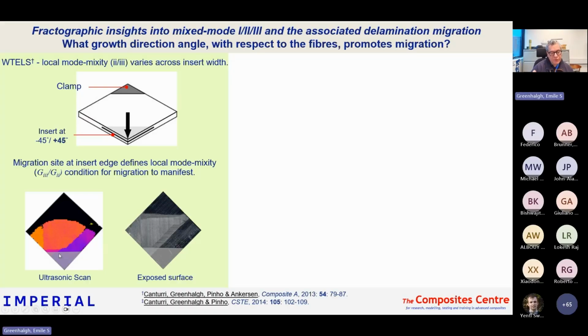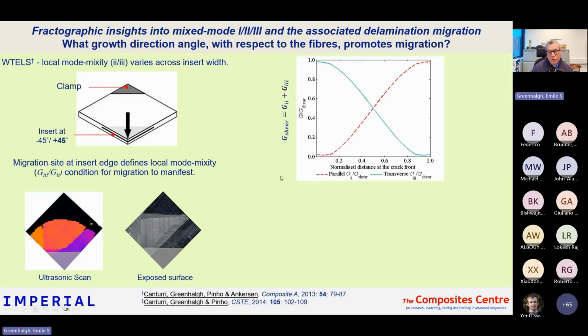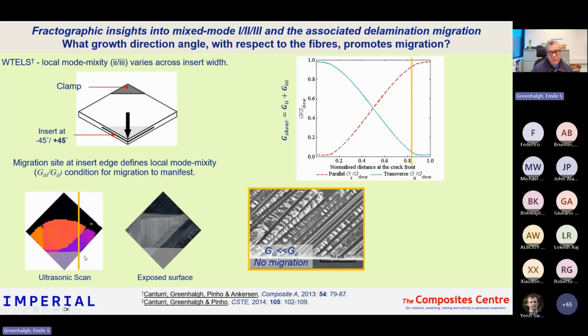And then by scrutinizing the fracture surfaces and doing ultrasonic time of flight scans, we started to be able to identify where that delamination had migrated. So this is a graph showing you the local mode 2 and the local mode 3 across the width of this specimen. So if you look at a region out here, for instance, here the local mode 2 is dominating. As you can see, the red line, and so we get cusps that are staying within the original defect plane.